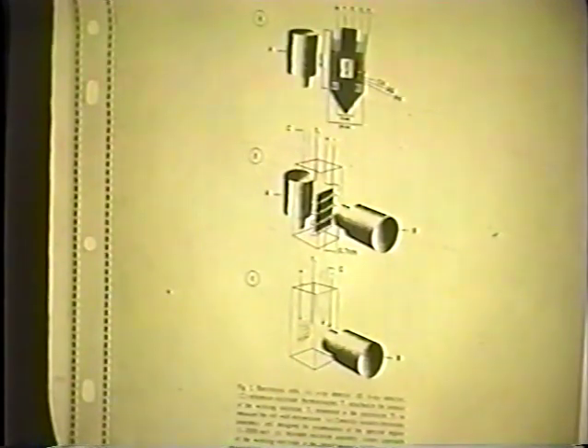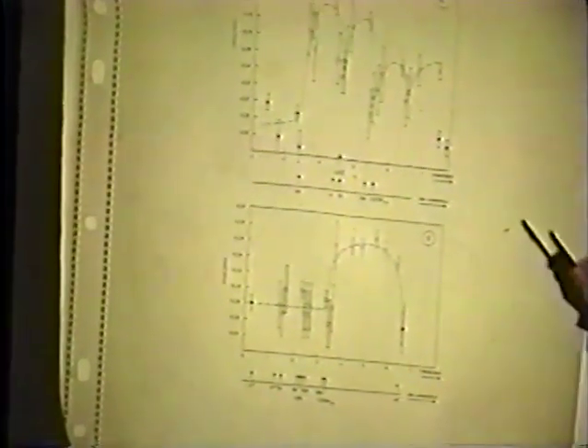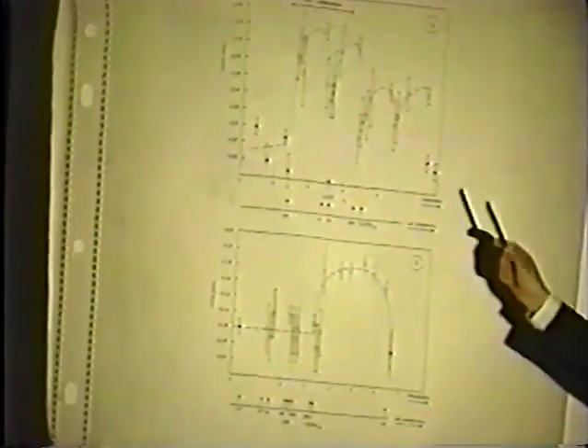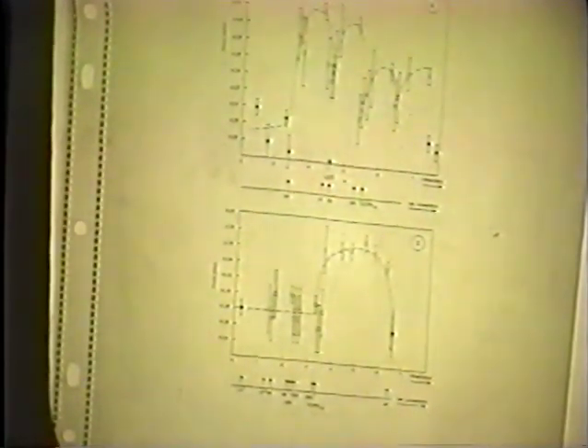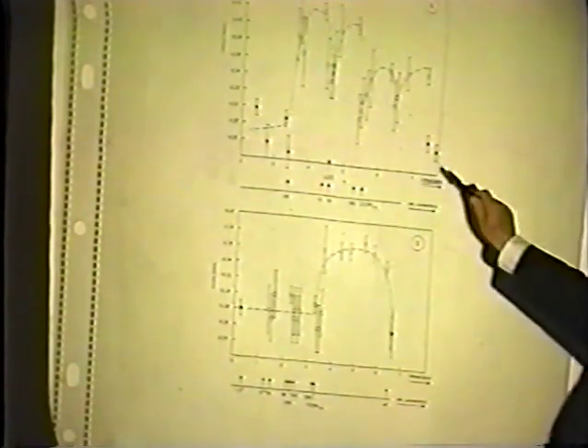Now, what are the results of this kind of arrangement? Well, in the first case, we see that the solid circles again are the background. The open are the experimental values. The first slide shows us the results between 15 to 3000 keV, the upper one on the carpet-like surface, and the lower one on the smooth surface.